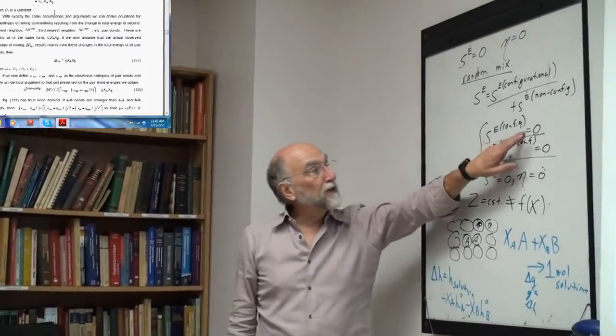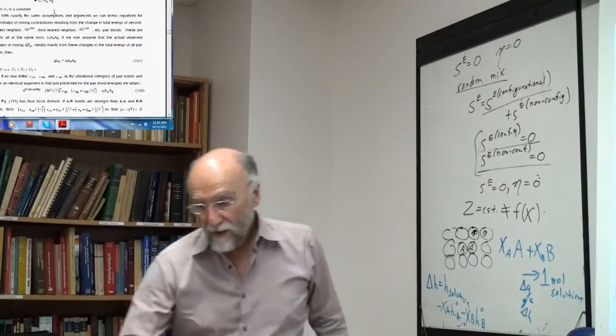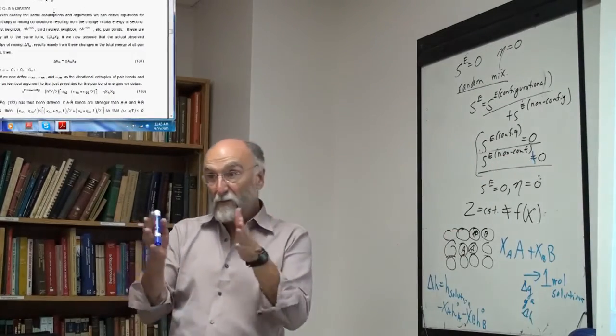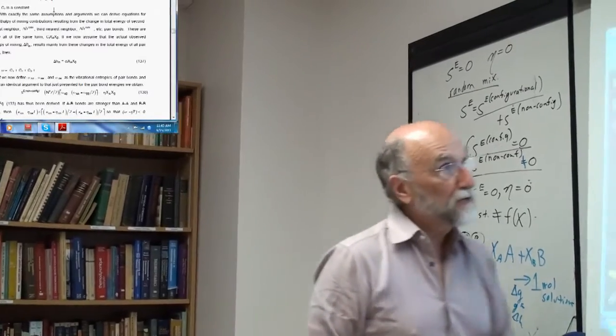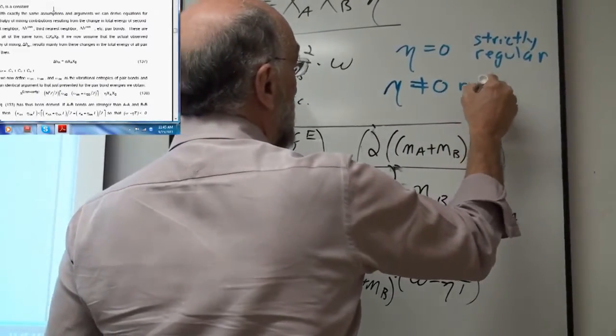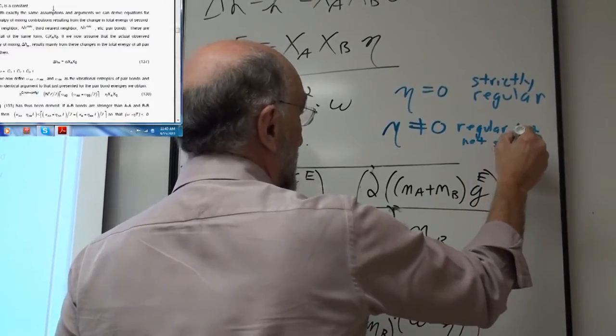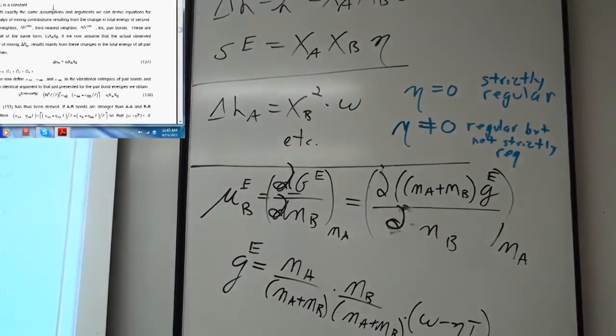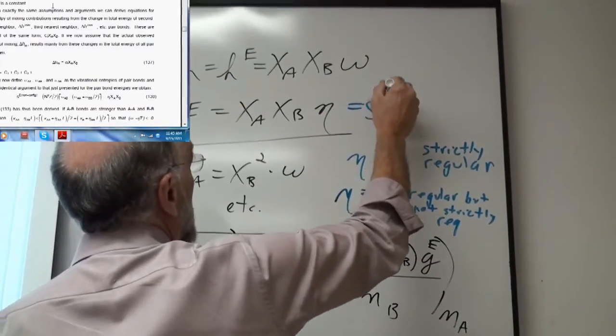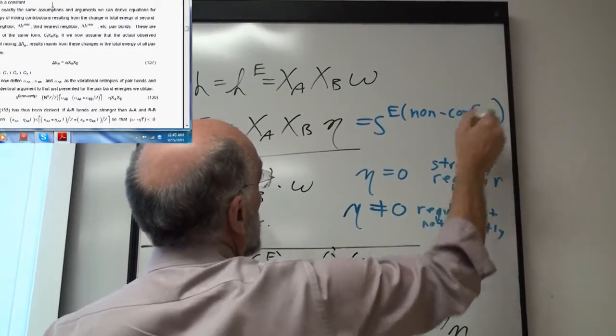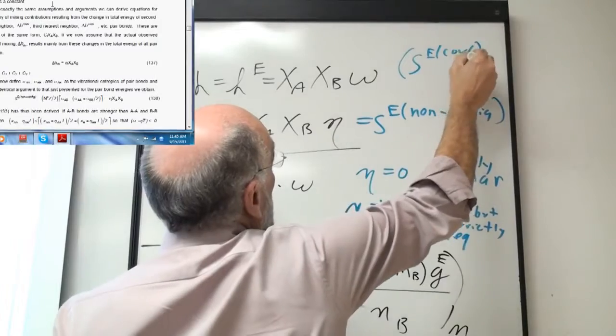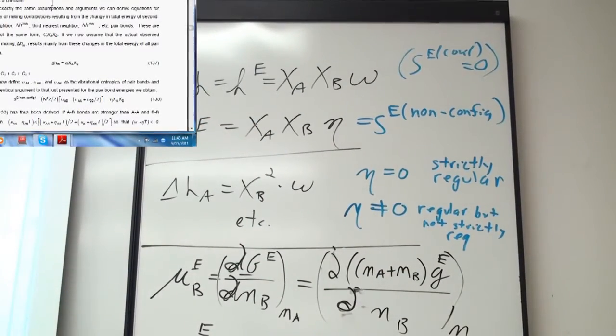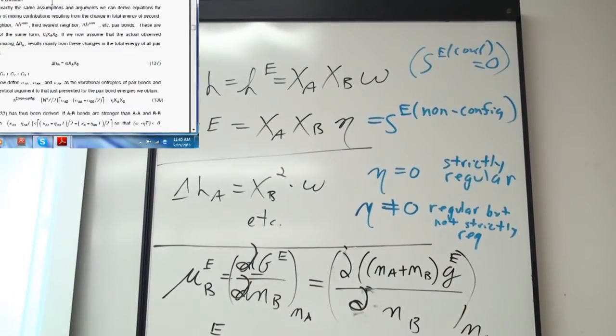So we must assume that the configurational entropy still is 0, and we're assuming that it's all non-configurational. The non-configurational is the vibrational entropy. So we're saying where eta does not equal 0, we have regular, but not strictly regular. For a regular but not strictly regular solution, we're still assuming that S excess equals S excess non-configurational. That is, we're still assuming that S excess configurational equals 0. So even in a regular solution where eta is not 0, we're assuming that all the excess entropy, in the model anyway, is non-configurational. So it's the difference in the vibrations of the bonds.